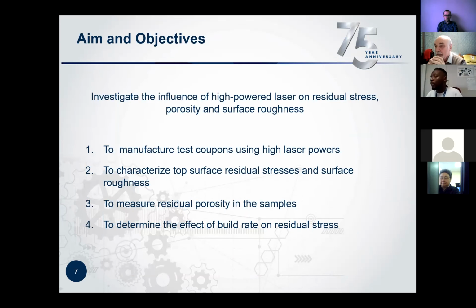Now, this brings me to the aim and objectives of the study. What we really wanted to do was to look at the influence of high laser power on residual stresses and porosity, and of course the surface roughness. The objectives here: we manufacture test coupons using high laser powers. We characterize them to measure the residual stresses at the top surface, and also characterize the surface roughness using microscopy. We then also did some characterization of porosity. And lastly, we were trying to see if we can correlate build rate with the development of residual stresses.